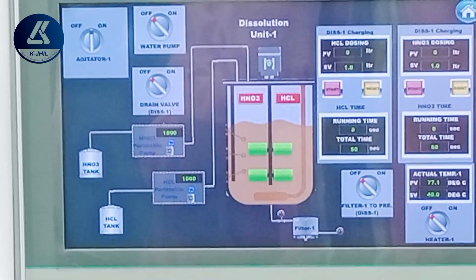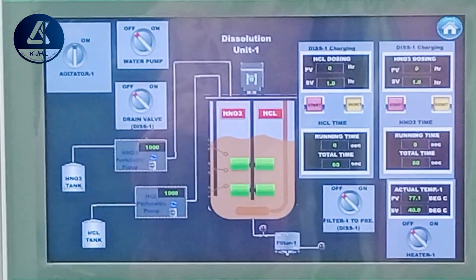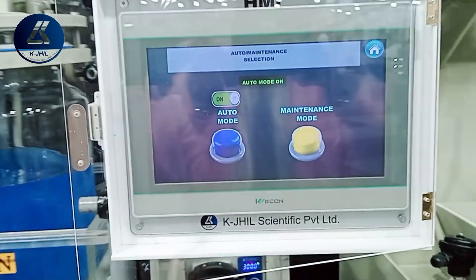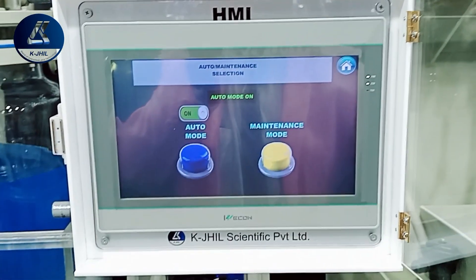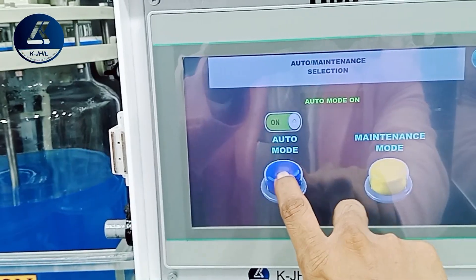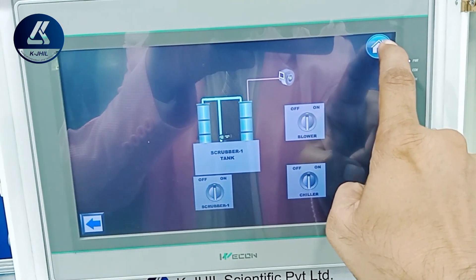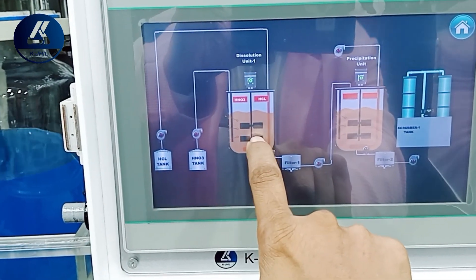The refinery process goes through five major steps: melting gold, dissolving gold in aqua regia, filtration and removal of other metals, then gold is precipitated out of the solution by adding a reducing agent like sodium bisulfite or stannous chloride. Finally, the precipitated gold is filtered out, washed, and the refined gold is thoroughly washed with water to remove any remaining impurities or chemicals before being dried.